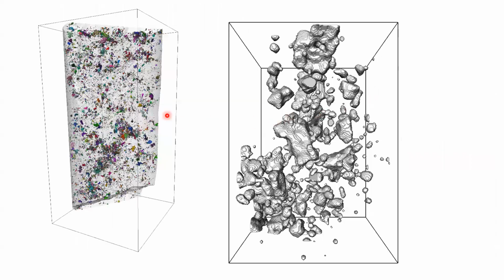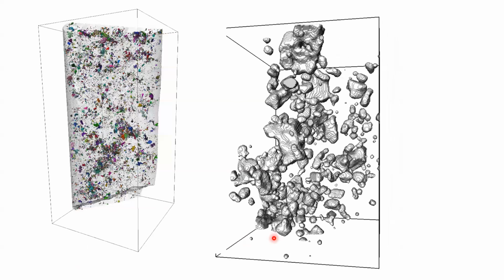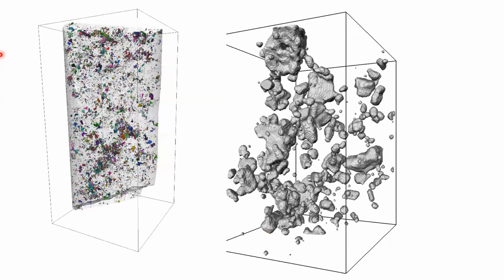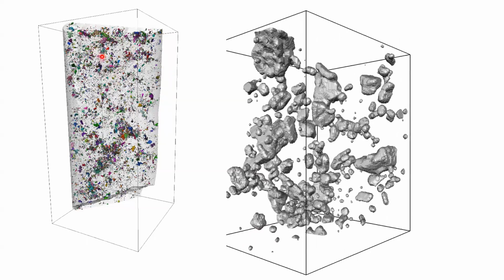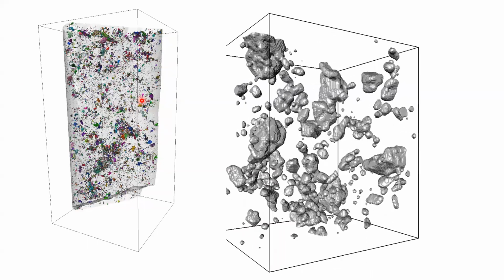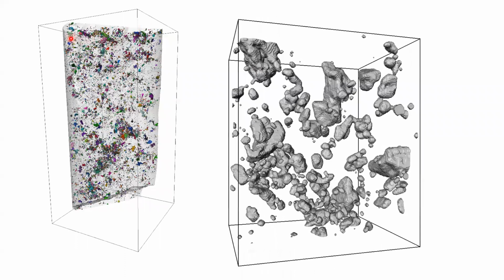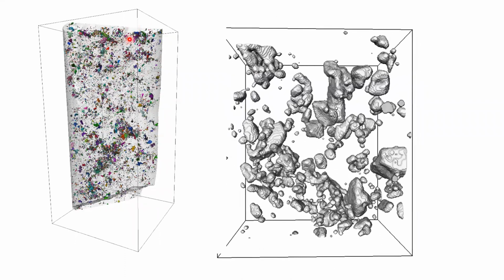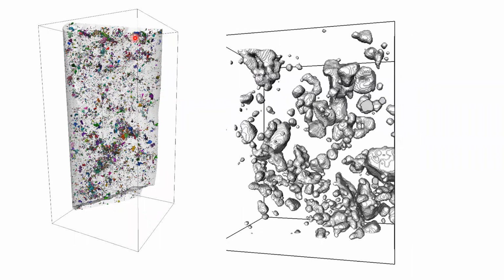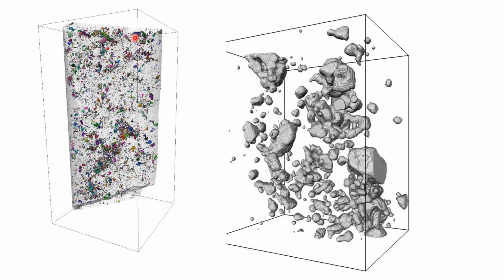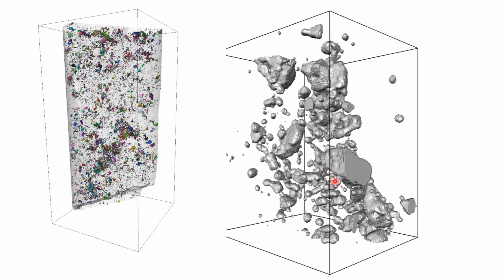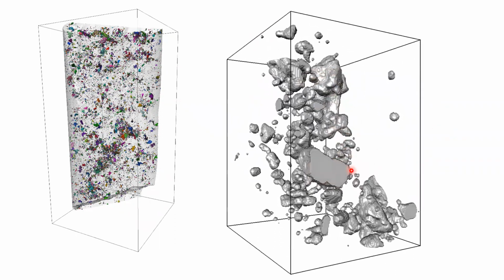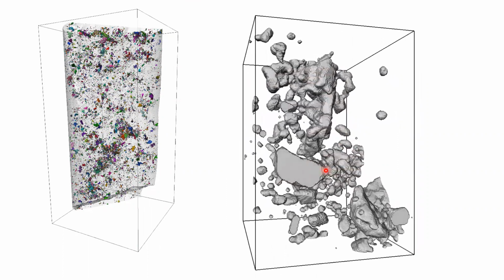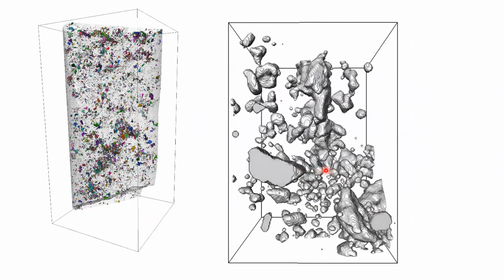I'll just show you one of these in 3D. I've persuaded this to run. There we go. So this is a MicroCT scan of this experiment. What you can see here is that the chromite's very heterogeneously distributed in the sample. And where we're getting clusters of these little new grains growing tends to be around the remains of the chromite that didn't melt during the preheating step. Those are these big ones here, leftover unmelted chromites. But these things seem to catalyze nucleation. There's a cloud of crystals around them.